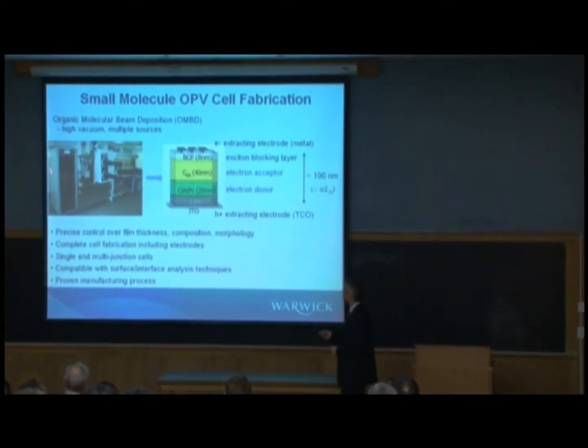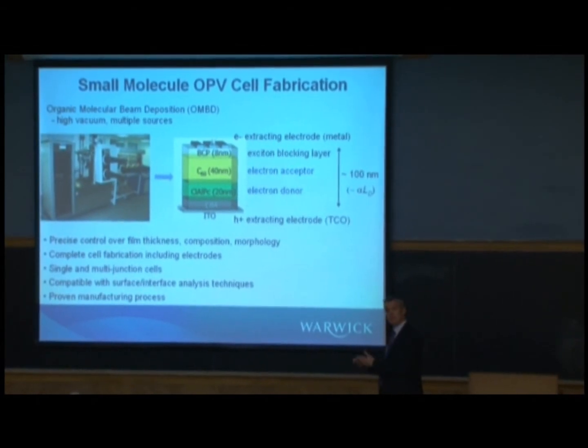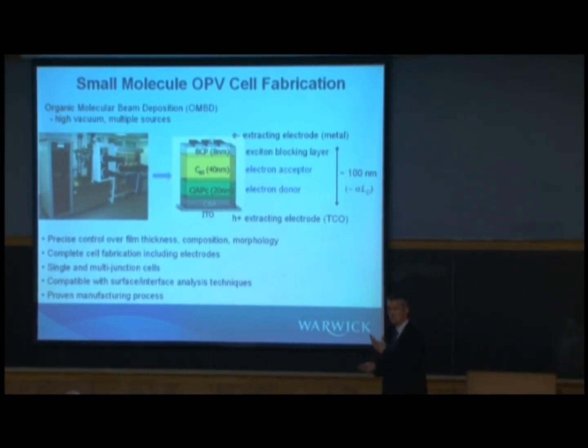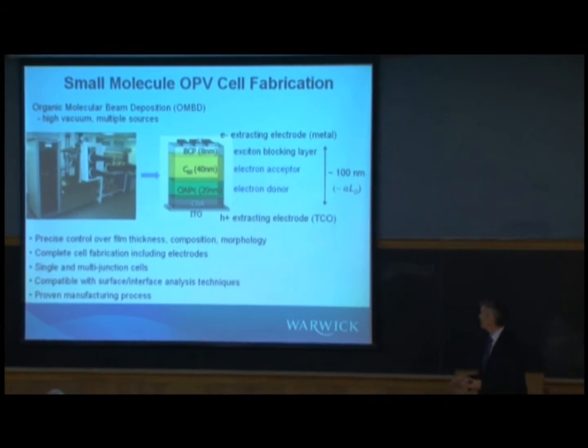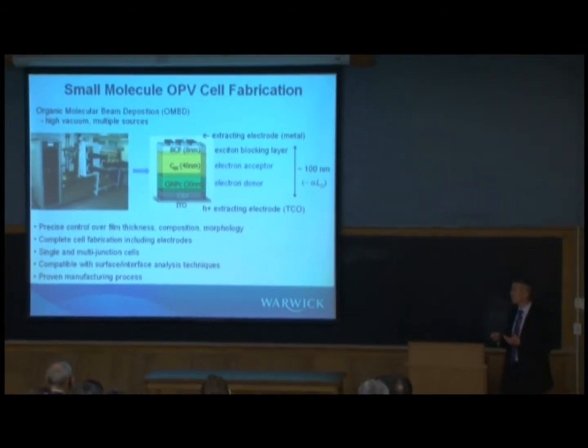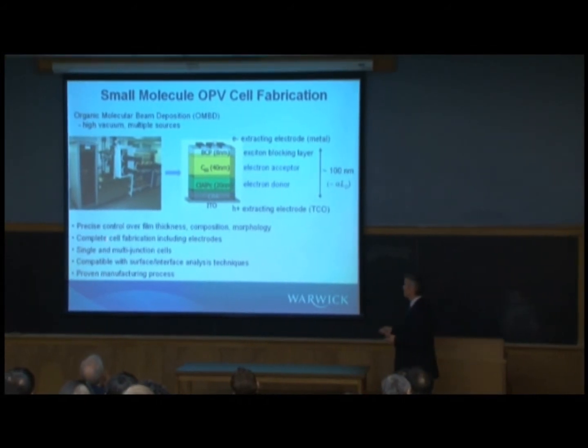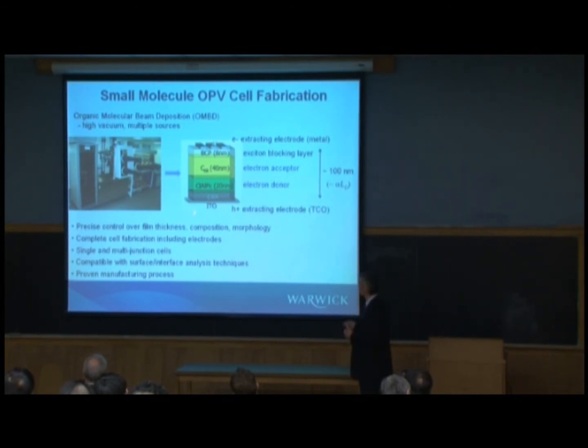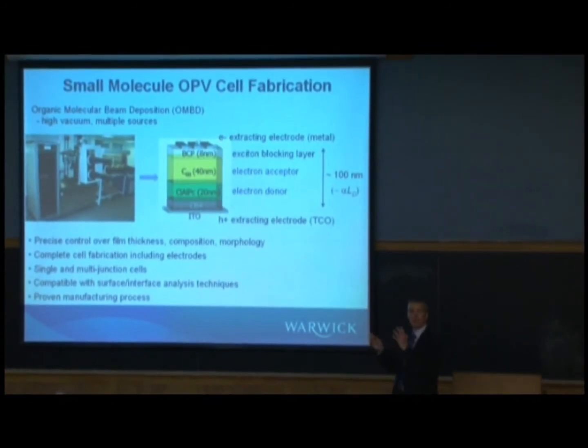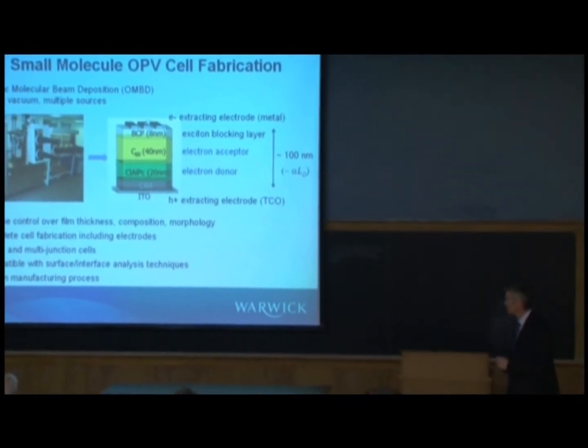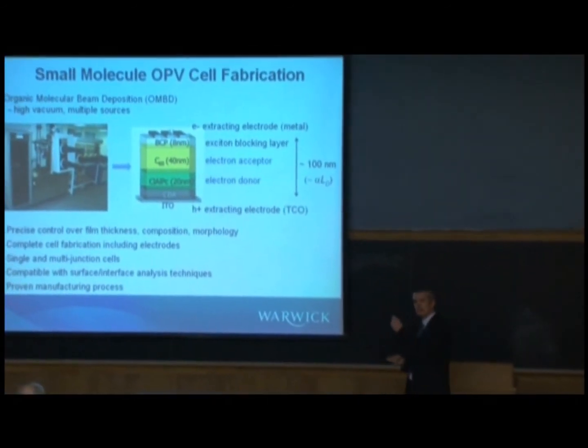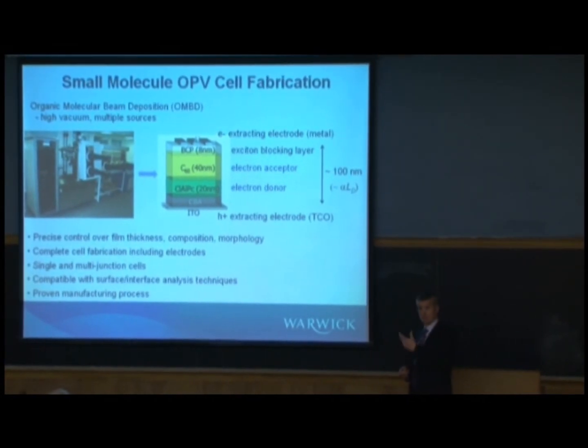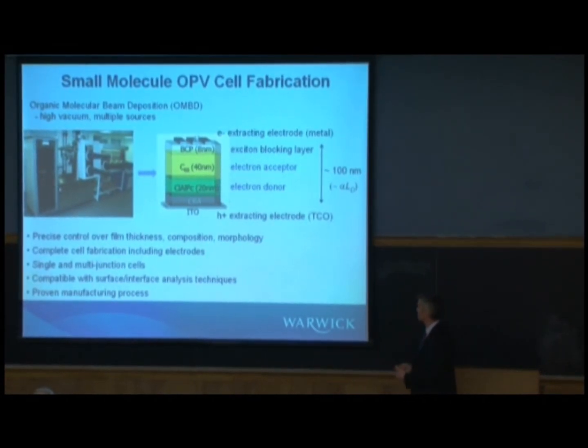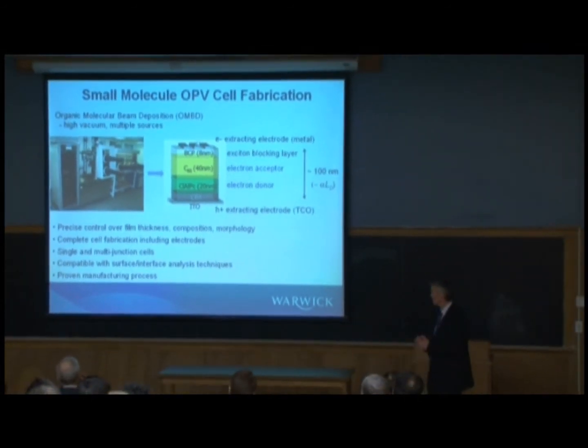The advantages of this technique are, because it's a vacuum thermal evaporation process, you get very good control over the film thickness, composition, so you can mix layers very straightforwardly, and therefore the morphology. You can make the whole cell in this system. You don't have to transfer to other systems, so you can deposit the electrodes and any other materials all in the same system, which is very convenient. It's compatible with putting down lots of different types of materials, so you can make quite complicated cells, single or multi-junction cells, which is more difficult when you're processing from solution, which is what you would do with polymers.